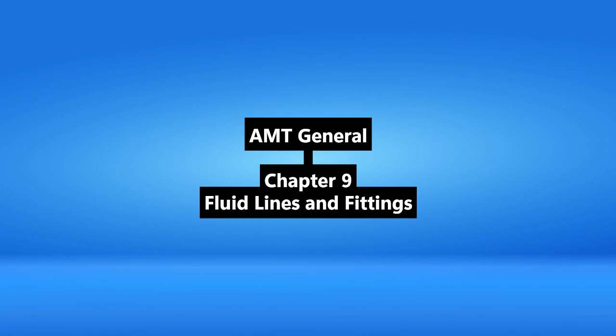Which brings us back to identification. Getting the material right is vital, especially for repairs. Visual checks aren't always enough, the source says. That's a key point. You might tell aluminum from steel generally, but telling specific alloys apart visually is very tough. So you rely on the markings? Absolutely. Meticulously compare markings on the replacement tube with the original. For aluminum, larger tubes often have stamped markings. And smaller ones use color codes. Yes, color-coded bands. Figure 9-1 in the material shows that. White for 1100 alloy, green for 3003, red for 2024.